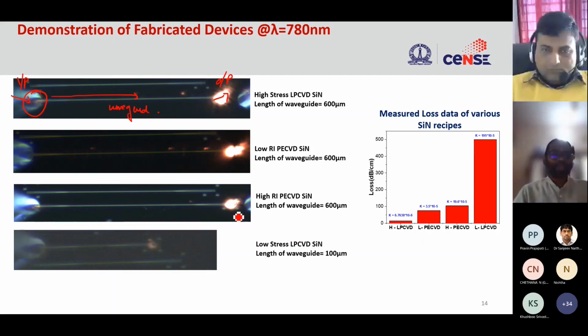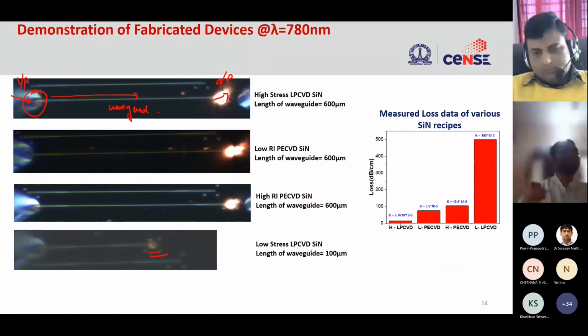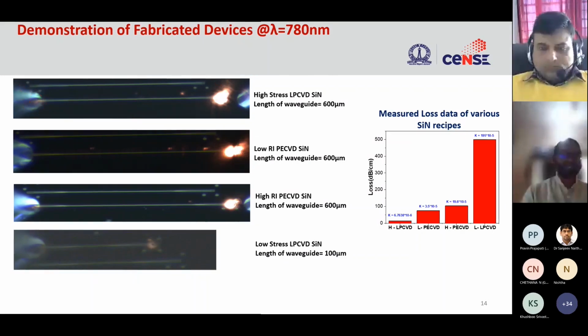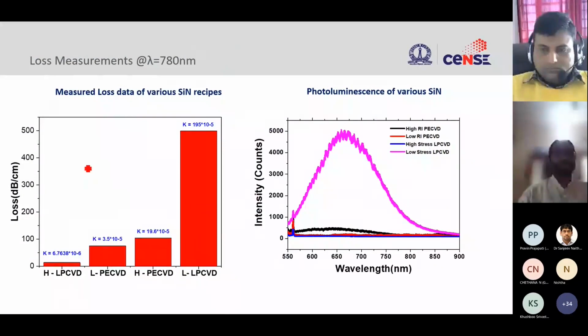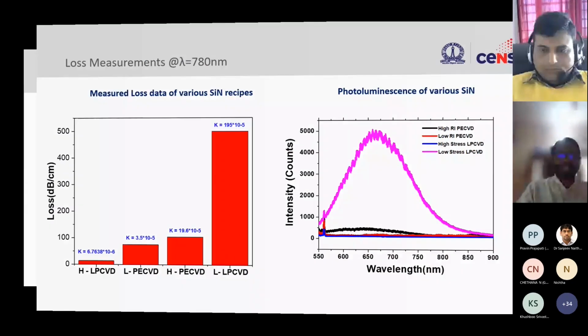And you can see that there are different structures on different materials that we have measured. This is the brightest that we can see, and this is the faintest. And we actually measured the propagation loss. You can see that the propagation loss correlates with the K value that we measured. So whatever material characterization we had done earlier, we were able to correlate with the actual device propagation measurement. So you can always do this material development based on just thin film characterization, and we confirmed it with our propagation loss measurement, and also photoluminescence measurement as well. So we have waveguides that can guide light at 780 nanometers with reasonably low loss.